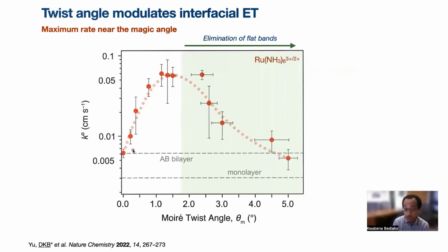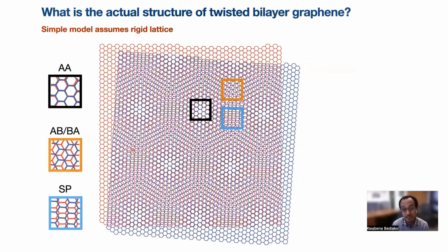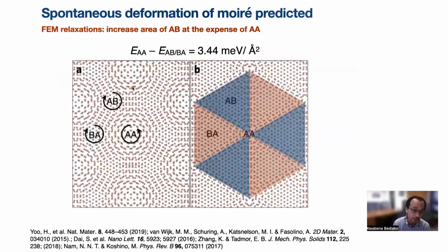So when I show you this picture here, it's of course a cartoon that assumes that the lattice is rigid, but this is not the case. It's been known for a while that the graphene lattice should relax to adopt a lower energy structure, where the relaxation mechanics are proposed to involve localized rotations of these AA regions that twist further to try to shrink their size, and these AB and BA regions that untwist. And so what my group tried to do was to find a way of measuring these local rotations and the resulting strain that we expected to observe more directly.